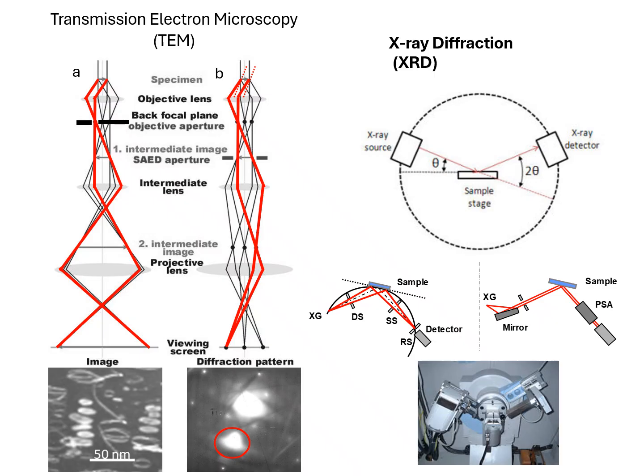Generally, what one detects is based on only single interactions, single scattering events. And it's not the same as electron diffraction, because the information we get down at the bottom of the microscope is the result of multiple scattering events through the crystal.